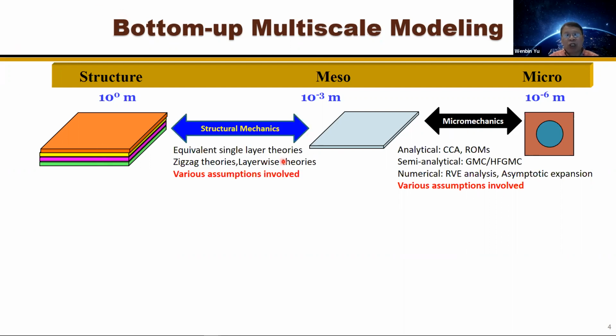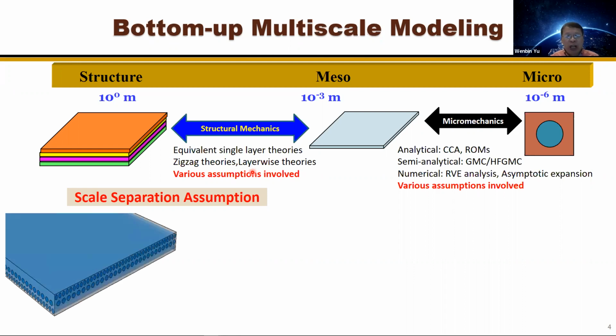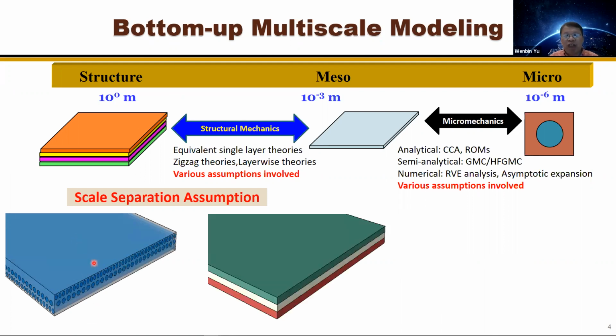Both micromechanics and structure mechanics are two separate subjects, and we have all kinds of models there, and various assumptions involved. The more fundamental assumption is what I call here the scale separation assumption, when you do this two-step micromechanics and structure mechanics. For example, you have a unidirectional fiber reinforced composite with perfect bonding. If you do this, basically you effectively replace the original structure with a structure made of three homogeneous layers. Then you shift the interface discontinuity. Originally the fiber and matrix interface now becomes a layer and layer interface. We create so-called artificial discontinuity. It would be okay if the fibers are much smaller than each layer thickness, which is true for traditional prepregs.